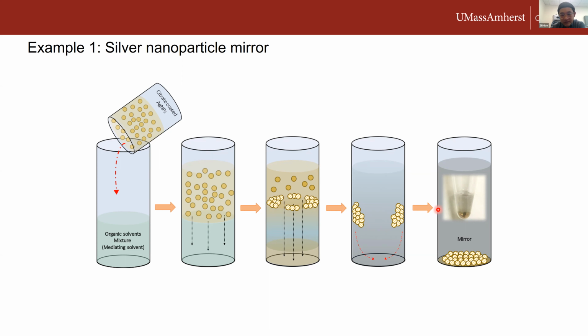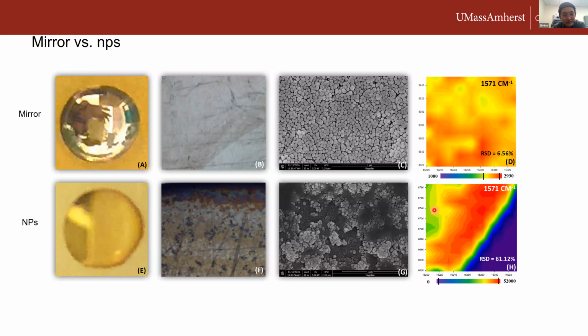So this silver mirror has many advantages. For example, it is very uniform. It creates very uniform signals. This is one of the examples we can see here on the top. On the top is the silver mirror, and on the bottom is the conventional silver colloid solution. Let's first take a look at the picture down here. The nanoparticles we usually test using the coffee-ring method, meaning when you mix your nanoparticles with your samples, you put them on a solid surface like a gold slide or aluminum foil slides.